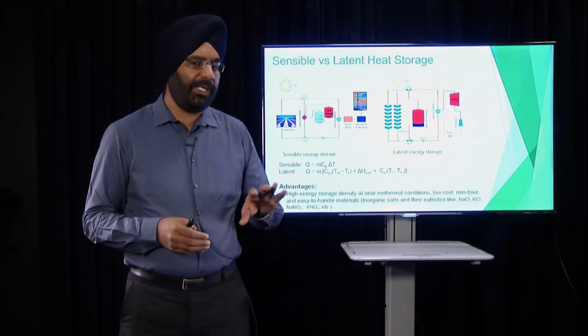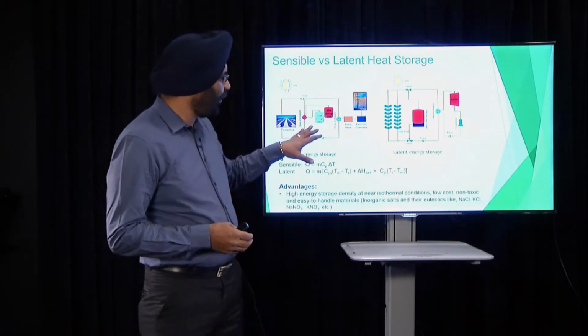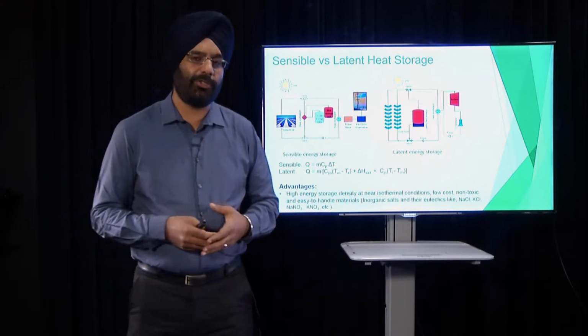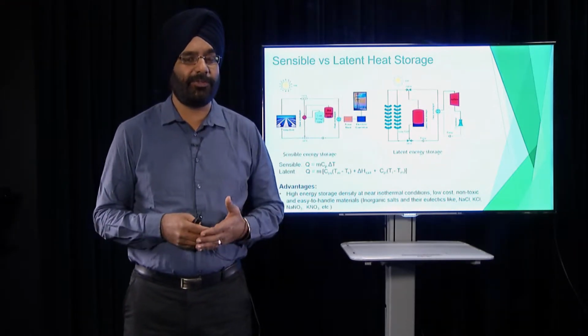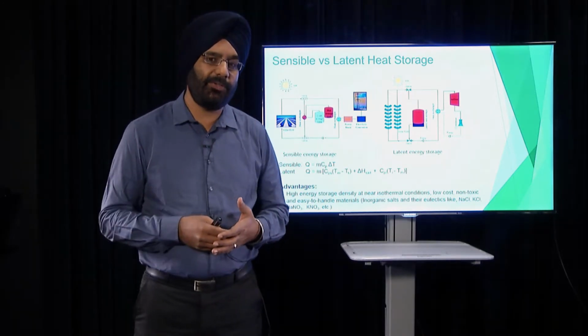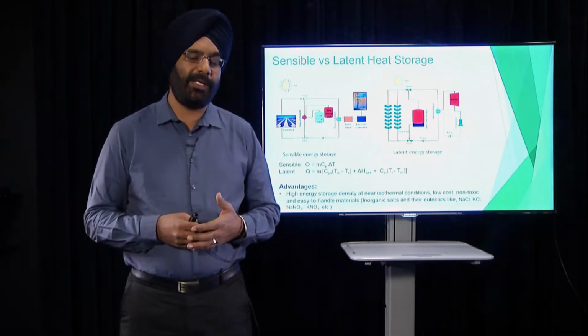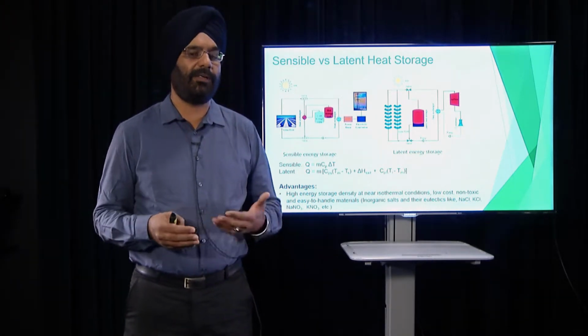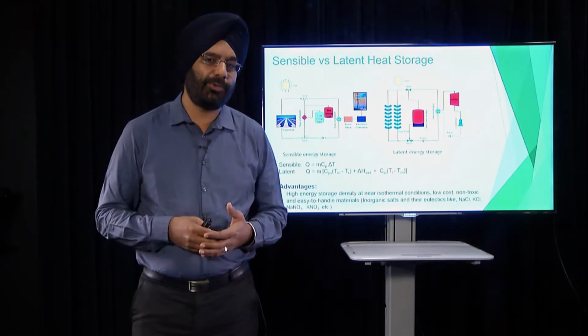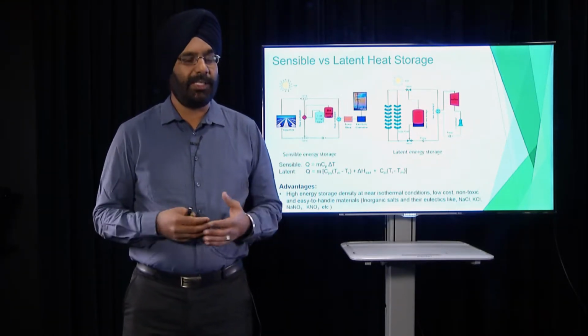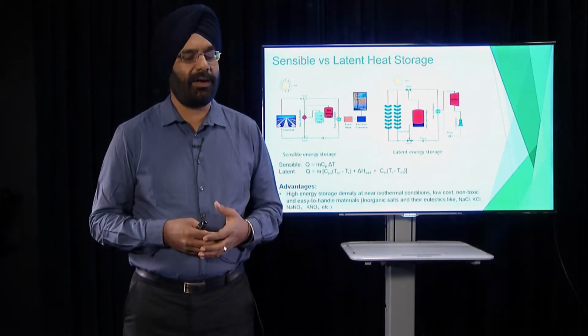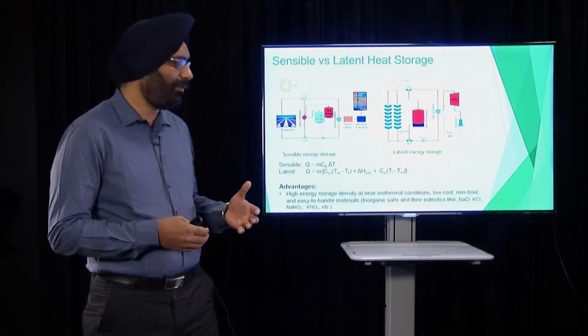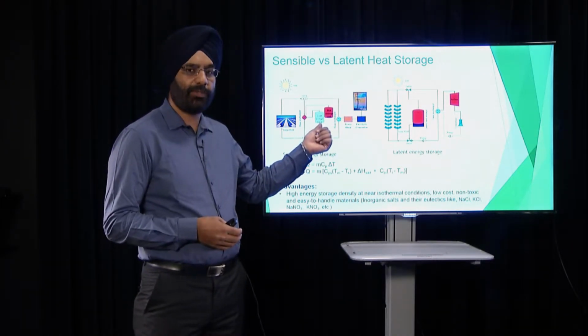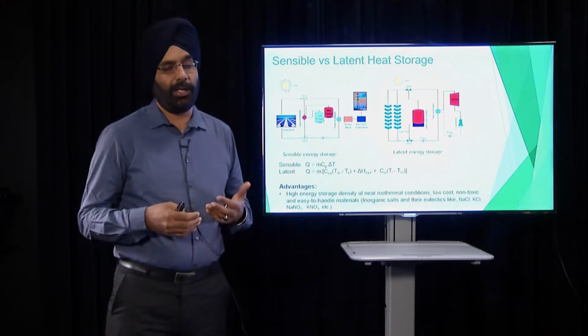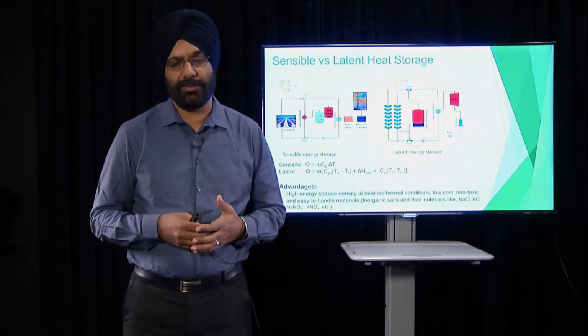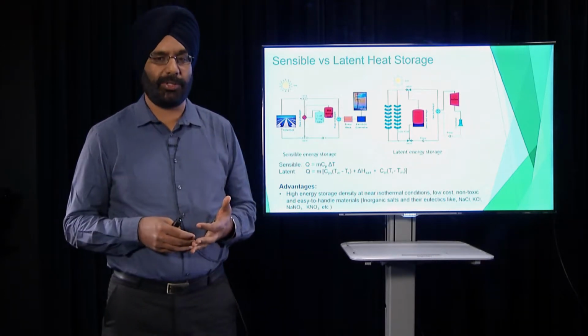The other problem, in addition to low energy storage density, with this technology is that it's dealing with molten salts. Currently the salt being used is a eutectic mixture of sodium nitrate and potassium nitrate, which has a melting point of around 225 degrees C. Inorganic salts in molten state are highly corrosive, and we're talking about pumping the molten salt from one storage tank into another, so a lot of corrosion may happen. So that's the other problem with this technology: low energy density and corrosion.